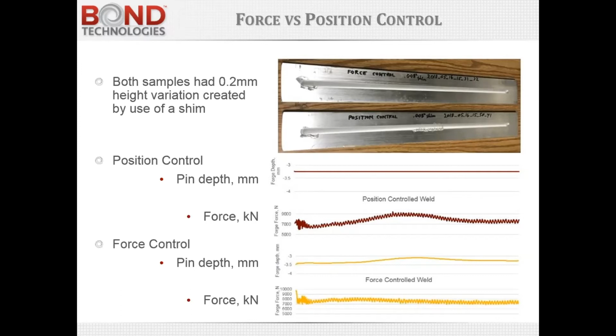So you'll see a couple examples in the picture up above. The top one is force control, the bottom one is position control. If you look at these graphs, the maroon or dark red lines show position control weld where the pin depth is controlled at a constant level. And you can see that as the tool welds over an intentionally created variation in height, the force varies. In the lower graph with force control, the pin depth varies as the force is held constant, which is a more desirable outcome. This results in a more consistent weld nugget and more consistent, more reliable material properties. So to do friction stir welding, it is advisable to use force control and use load sensors to be able to measure and close that loop.